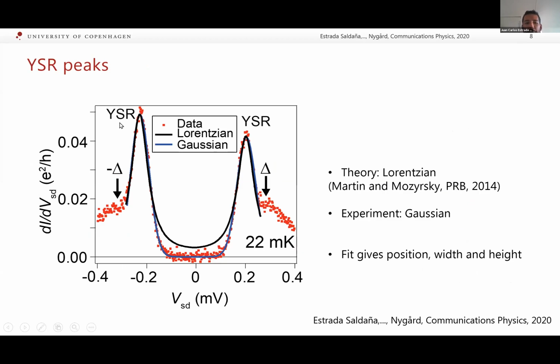And now let's look at how the actual YSR peaks look. So these are the two YSR resonances inside the gap. This is where the gap is at delta. And well, we saw in this paper that these YSR states in the presence of quasi-particle relaxation should acquire a Lorentzian line shape. So we fitted our data to the sum of two Lorentzians, because we have two peaks. And what we saw is in the black curve, and this doesn't fit the data. The data is in the red dots.